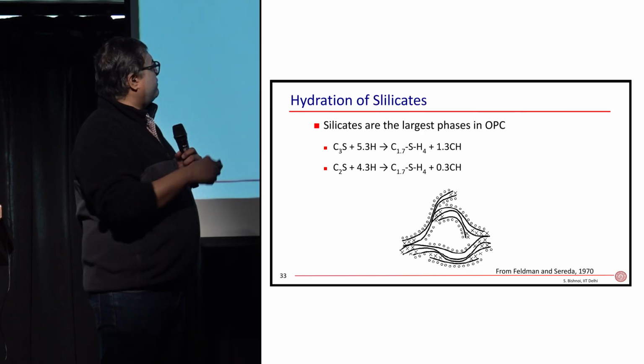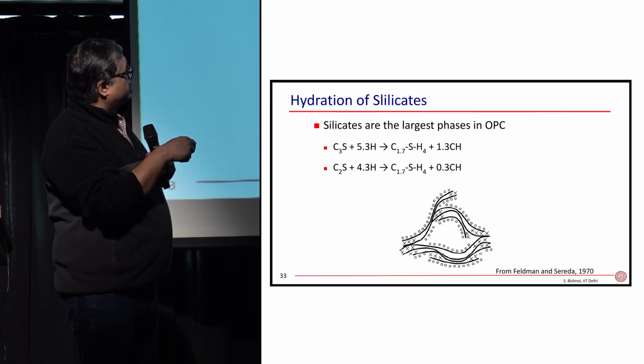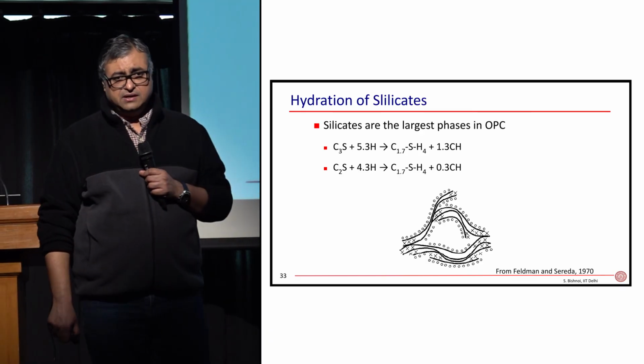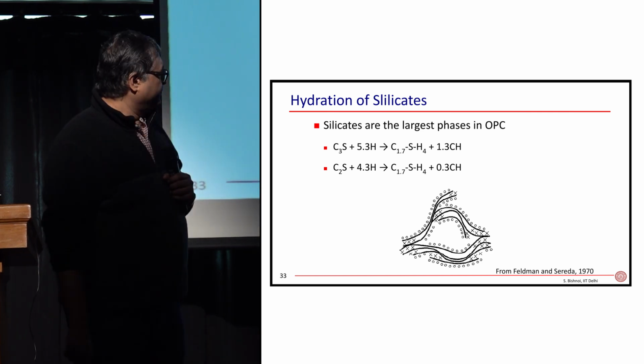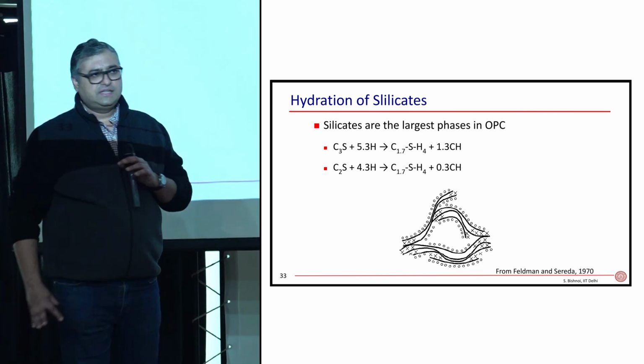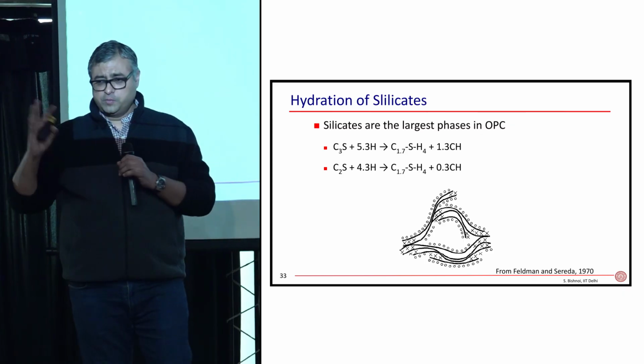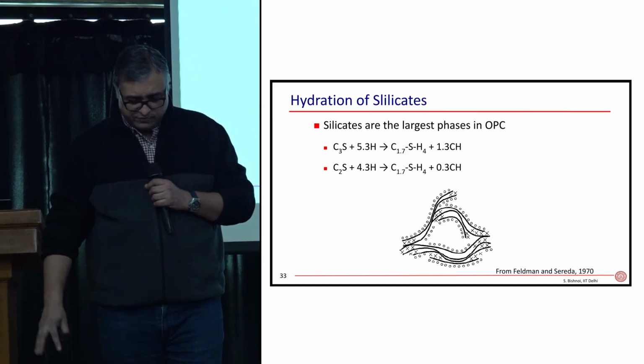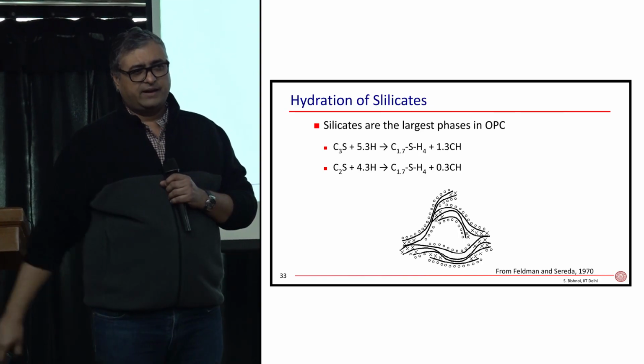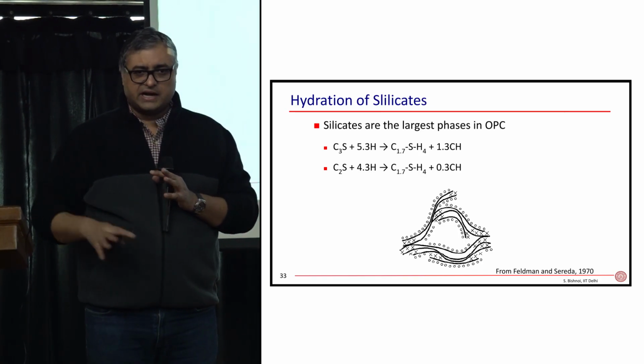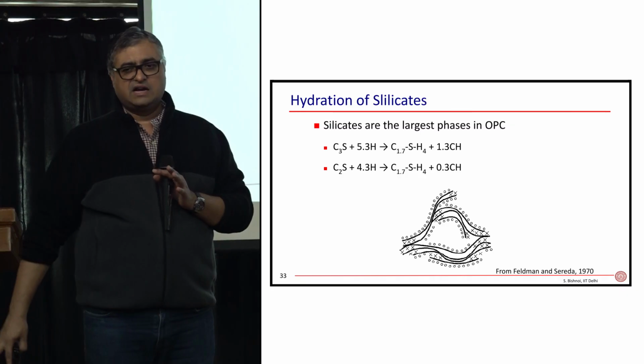Now the CSH that I've written over there, I have dashes in between. I have those numbers 1.7 and 4 over there. This is C3S and C2S react with water to produce this calcium silicate hydrate, and what I've written over there are some numbers. These numbers are not very sacrosanct, not very well defined.